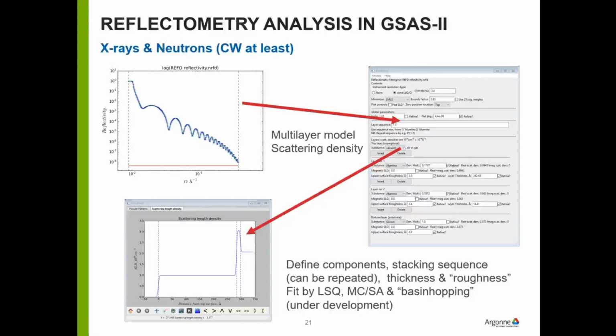So we then model this with substances which are layered on top of the surface. The bulk is here. Then there is another layer of stuff here, and another layer of stuff here, and then you're to the vacuum on the outside. So the reflection is done off of this side of the surface. You can define whatever these components are. It doesn't make any difference what their structure is. What matters is their composition. They can be repeated. You have multiple layers.